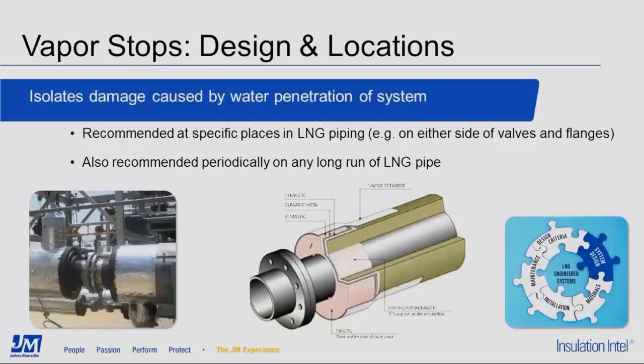In the left picture, you can see a vapor stop applied to a triple-layer staggered butt joint on either side of a flange. In the right drawing, you can see the details of one design for a vapor stop. We will not be discussing the details of vapor stop design today, but the key is that the vapor stop seals the end of the insulation and connects the pipe to the primary vapor retarder with a low permeance barrier to longitudinal passage of water or water vapor.